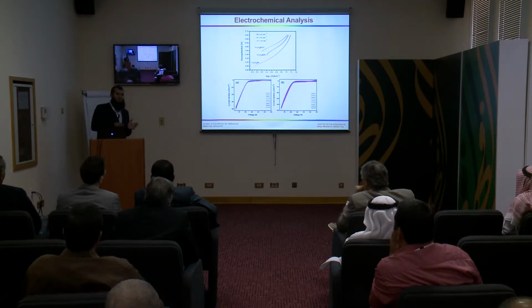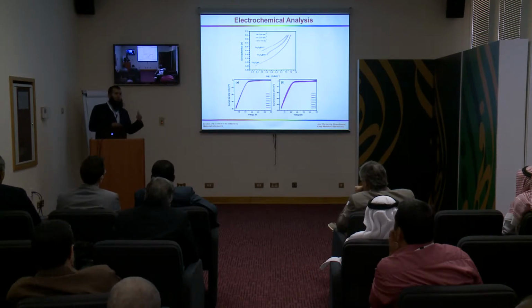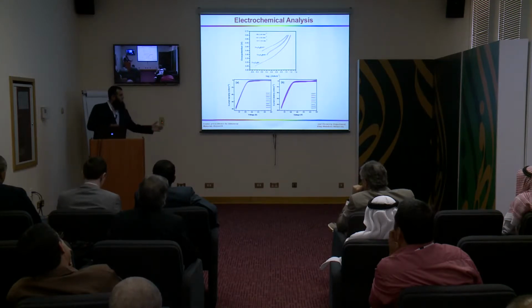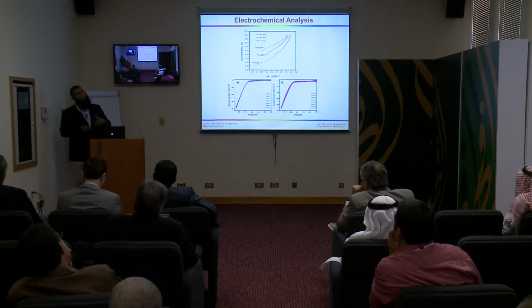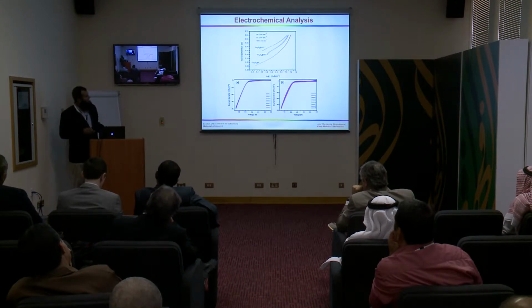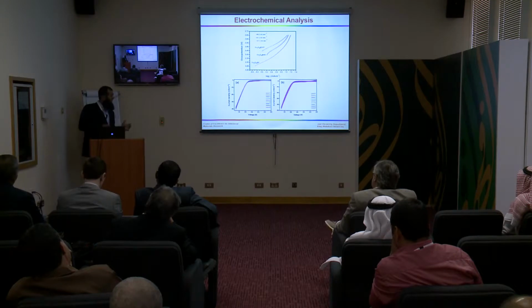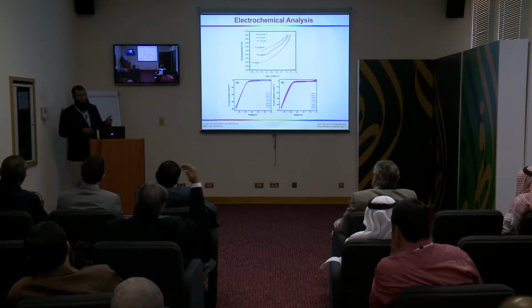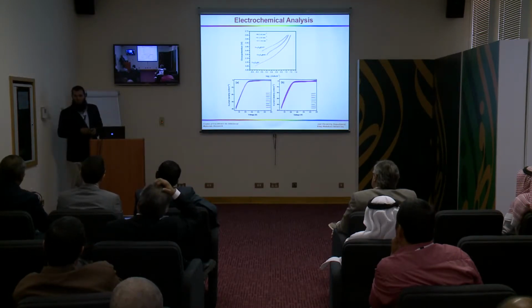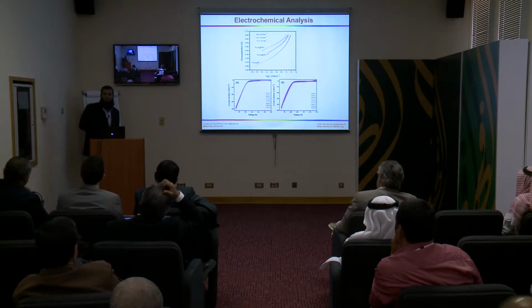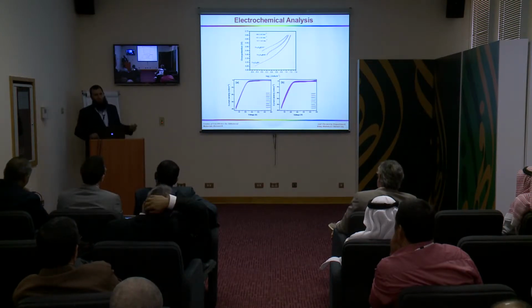In this case, to check the stability, we kept the electrode in the system for a long time, and after several minutes, sometimes 10 minutes, sometimes 20 minutes, we checked the stability while running the system. After each 15 or 20 minutes, it was still stable. So it indicates that the material is stable for a long time.